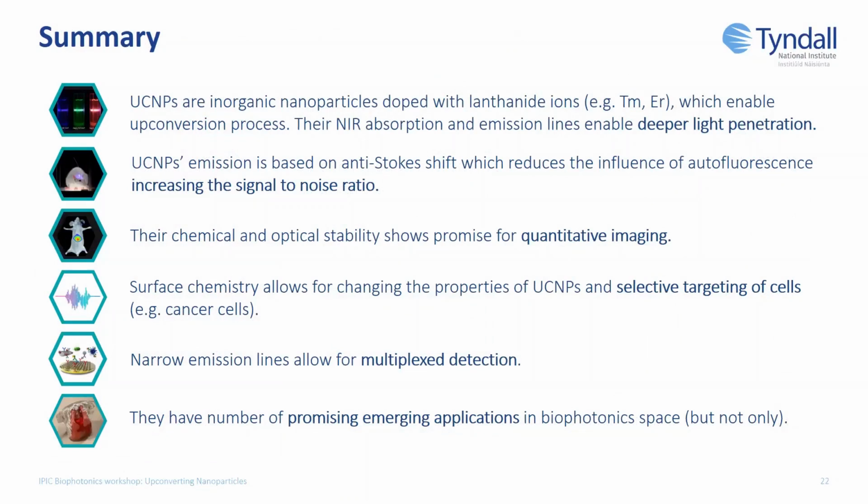So in general, upconverting nanoparticles are inorganic nanomaterials which are doped with lanthanide ions, and they provide us with great optical properties for achieving deeper light penetration and a lot of other benefits for biophotonics applications. For example, increasing the signal to noise ratio thanks to reduced autofluorescence. We can also work with quantitative imaging, and because of such an ease in which we can modify the surface chemistry, we can selectively target different cells. So they really do show promise for a lot of biophotonic applications.